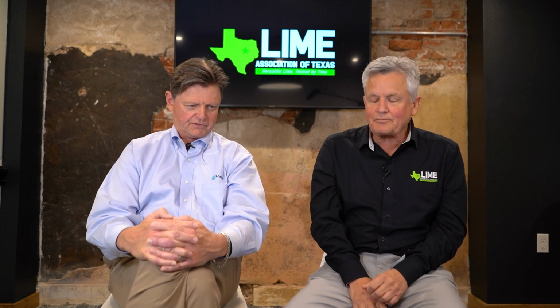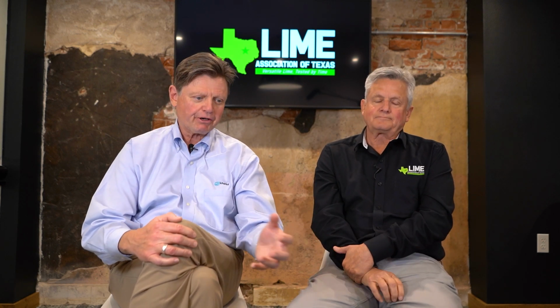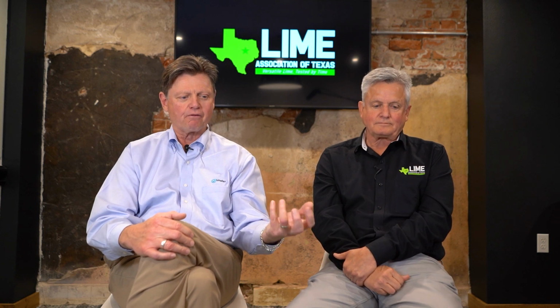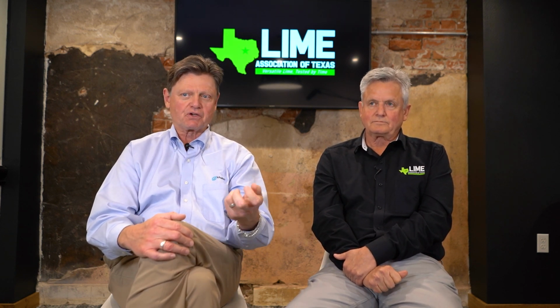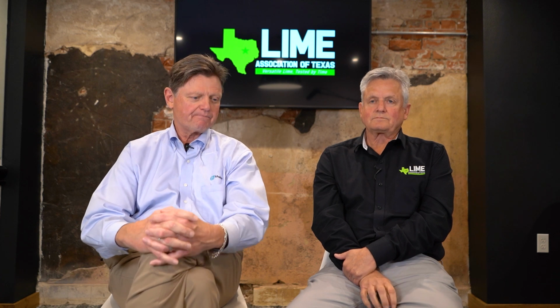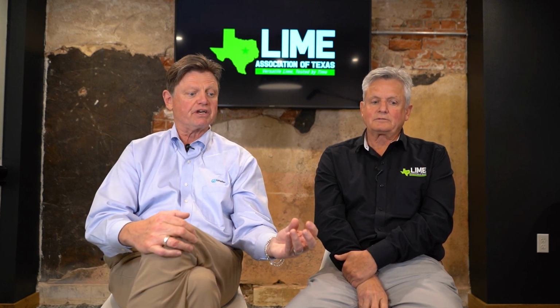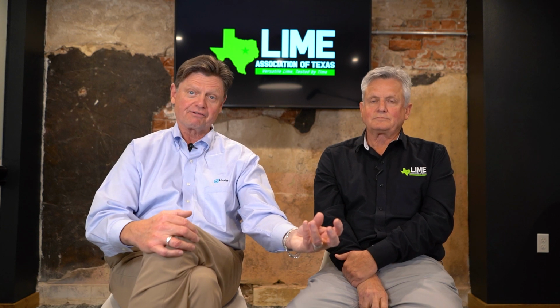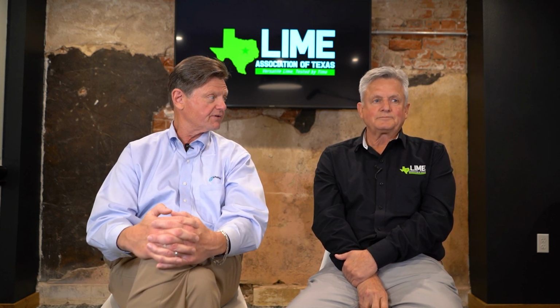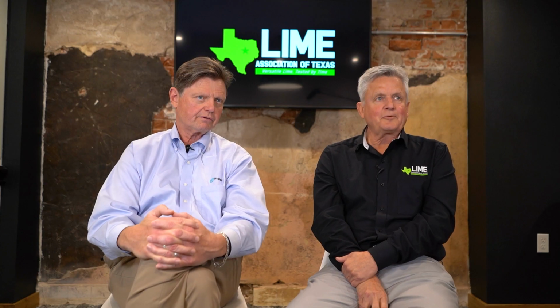Some bases are what we call dirtier, and so they may have a fraction of that overall base that is clay, and so we will see lime can be used to combat the clay fraction of that base material, but it'll still be used in conjunction with some other additive to get strength and those types of things in that material. When you typically see lime used in base, it would be in South Texas or some parts of West Texas where you have caliche base, which is really a base material, but it does have, as Larry said, dirty.